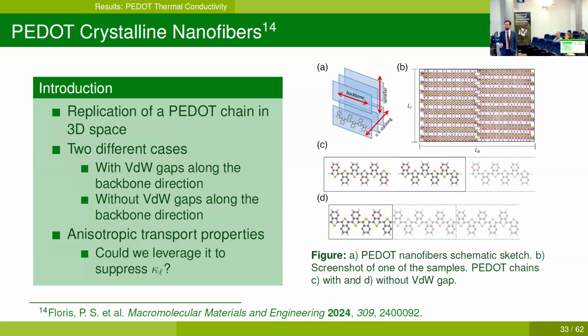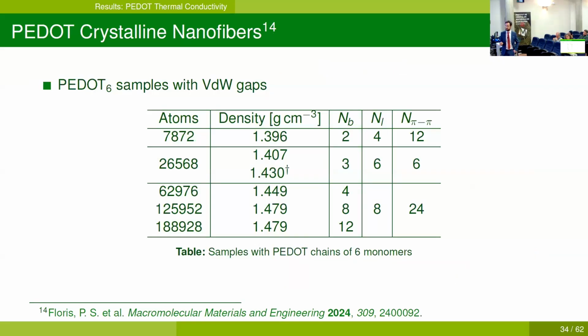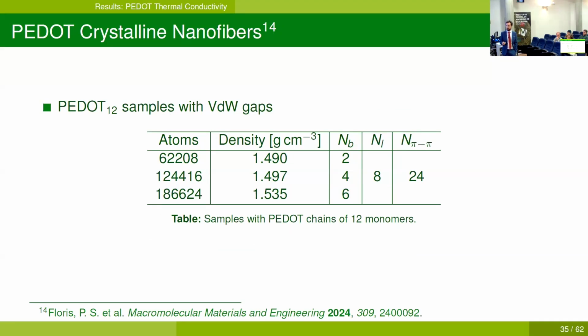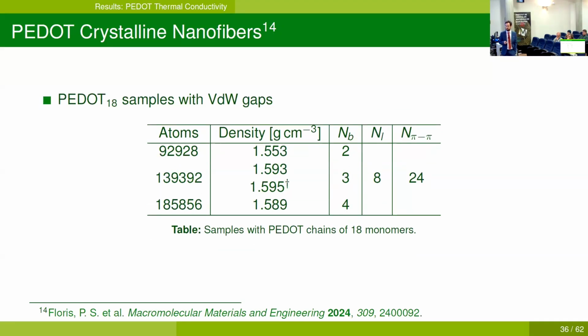We, of course, expect this system to have anisotropic transport properties since the transport mechanisms along the different directions are very different. And we want to know if we could leverage this anisotropy to suppress kappa L. This is a summary of the samples that we created, also in this case with PEDOT chains of 6 monomers, where you can see the number of replications in space, number of replications along the backbone, along the lamellar, and pi direction. Same things for PEDOT chains of 12 monomers and PEDOT chains of 18 monomers.